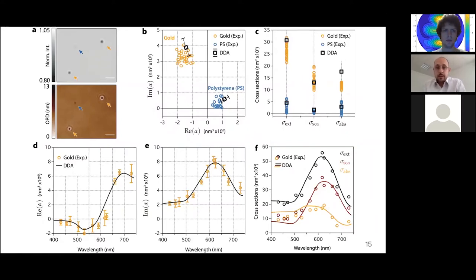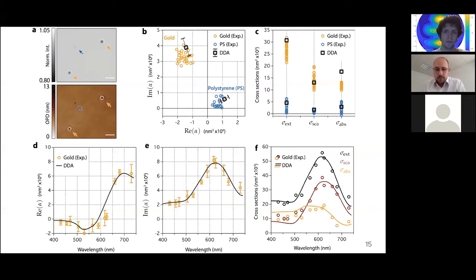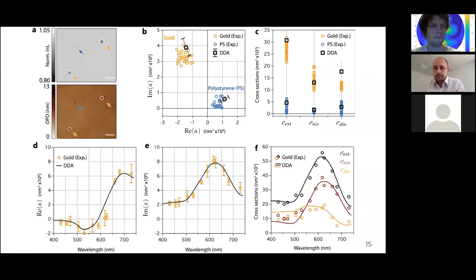This technique can be used as a metrology technique for nanophotonics. Today it is very important to develop metrology tools in nanophotonics because more and more new materials are proposed — plasmonics, dielectric materials, hybrid nanoparticles, more and more complex nanoparticles. When the particle is very complex, it is very hard to predict optical properties or run numerical simulations because you don't necessarily know the permittivity of the material. At some point, the only way to characterize the material is to measure. With one single measurement, you retrieve all the optical properties of the nanoparticle.